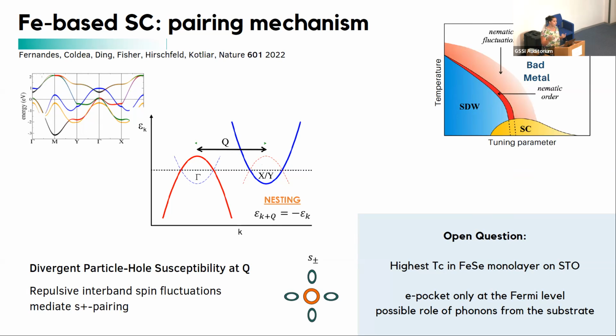And when this is perturbed with doping, this can provide an effective attraction between electrons, and this interband repulsive spin density wave exchange is mediating an S plus minus symmetry pairing, in which the gap on the hole and the electron pockets will have a different sign.